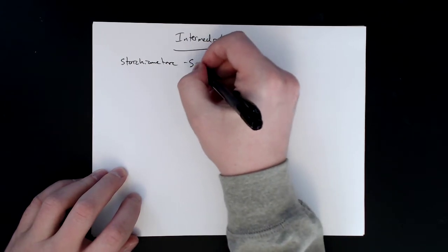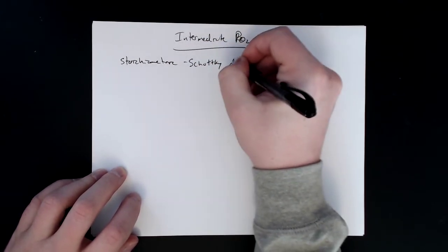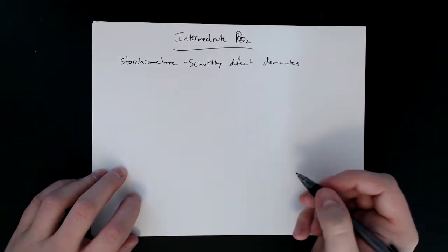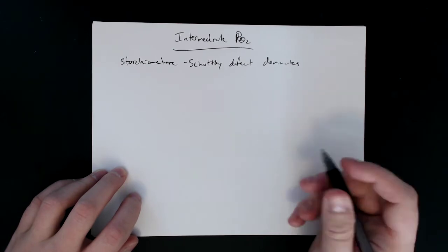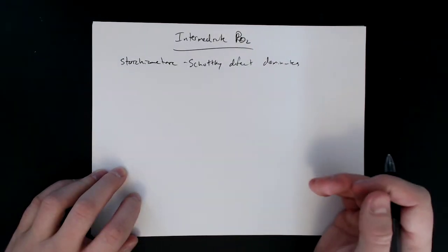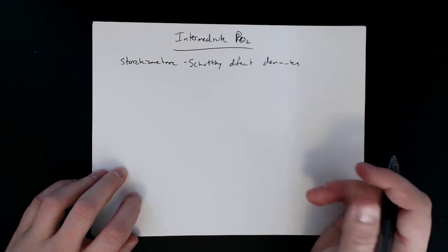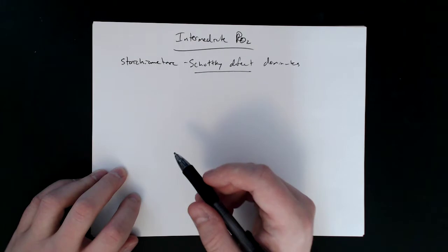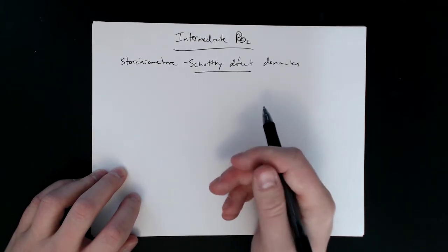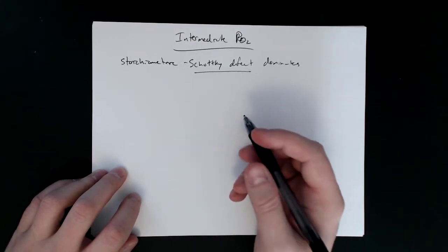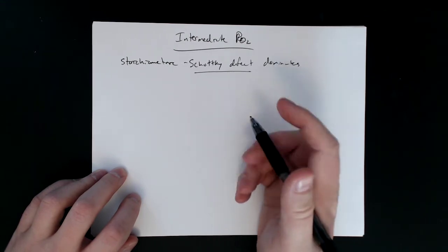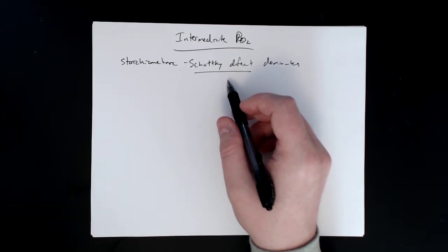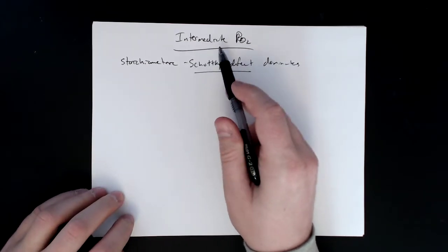Schottky defect dominates in these intermediate ranges where we don't have the effect of low or high oxygen partial pressure. So we have the Schottky in this region. Others might have semiconductors, and then the intrinsic electronic defect would dominate. But in this case, we're going to say that for this ceramic, Schottky defects are the predominant species that happens when there's really no effect of PO2.